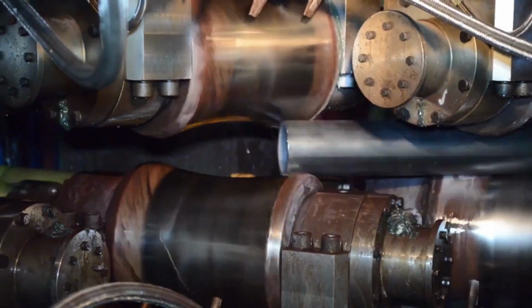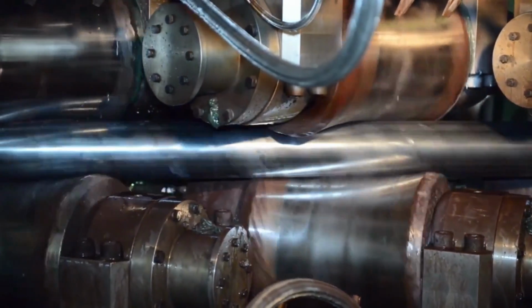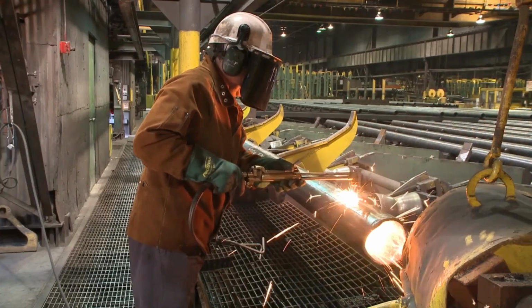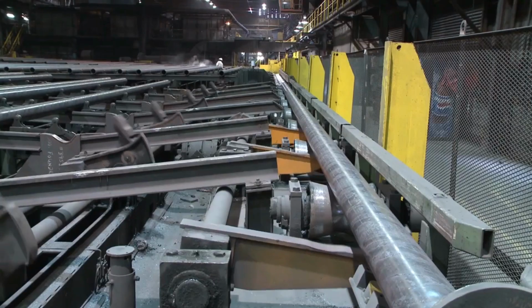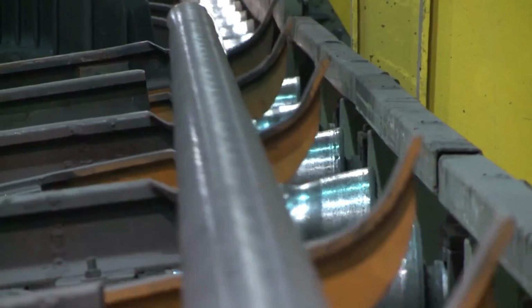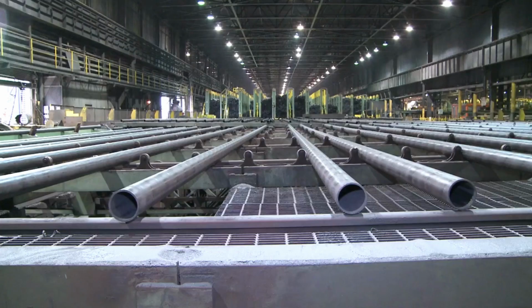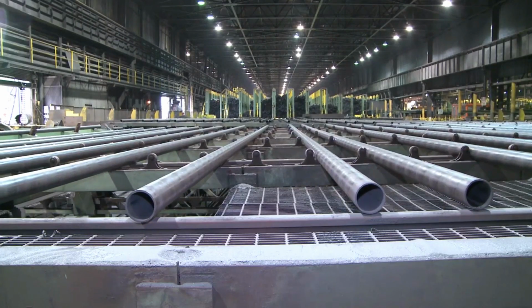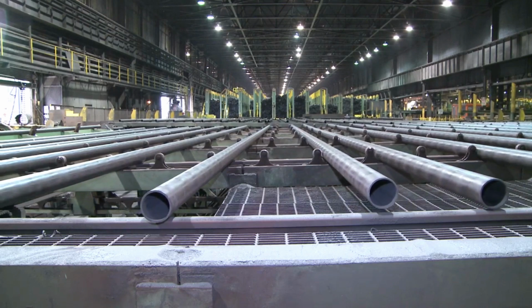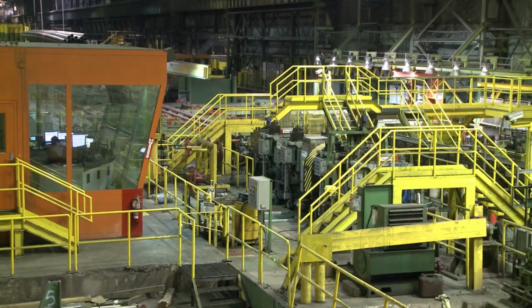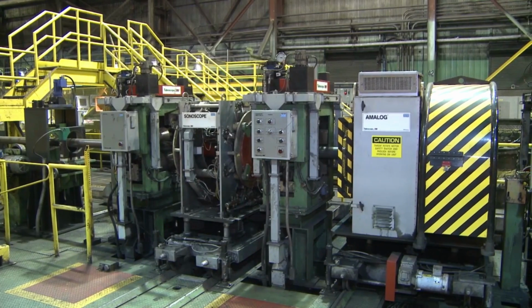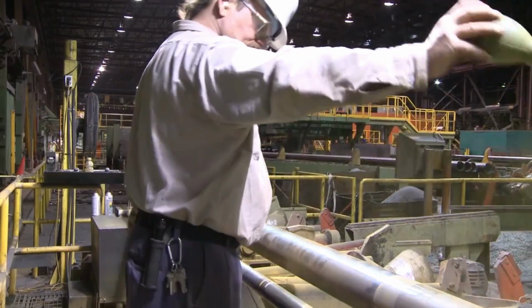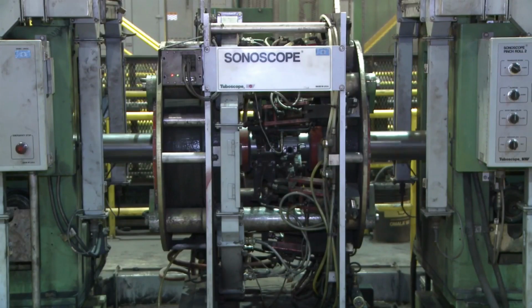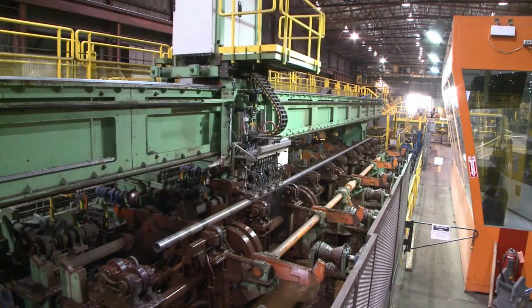tolerances. The pipe is then straightened on a rotary straightener while still hot. Once samples are taken for testing of physical properties, the heat-treated and tempered pipe is transferred to a cooling bed where the pipes are once again cooled to ambient temperature before being ready to proceed to finishing. The finishing process begins with non-destructive testing. NDT practices used at the mill include magnetic particle inspection, electromagnetic and ultrasonic testing, as well as visual inspection.